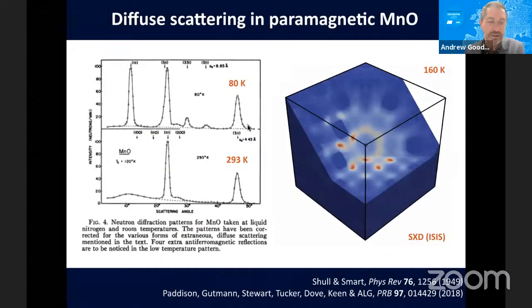And of course, diffuse scattering has long been known about. Here's an example from the neutron community, a paper that I'm sure is dear to many people listening in. It's the work of Shull and Smart on antiferromagnetic ordering in MnO. So this is the canonical antiferromagnet. This peak here effectively won a Nobel Prize, basically showing the existence of antiferromagnetic order. MnO undergoes this transition at about 120 Kelvin, but even at temperatures above that, when it's nominally paramagnetic, you still see broad diffuse scattering in that same position.